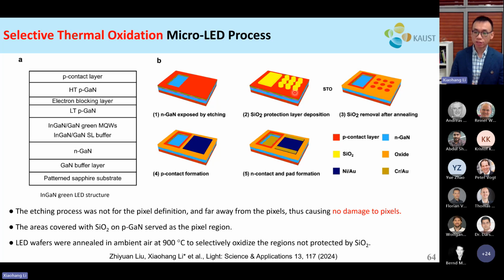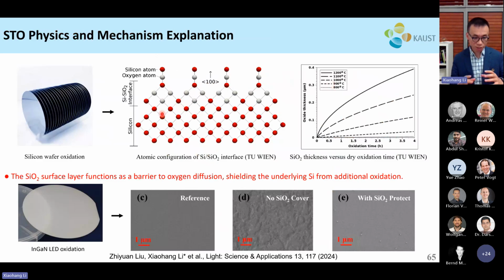And then after the oxidation, we remove the silicon oxide. So basically, the area below the silicon oxide is mostly not impacted. It still maintains the P-GaN PIN structure. But the area that is outside the silicon oxide protection layer will get oxidized by about a few hundred nanometers below the surface. Okay, so we utilize silicon oxide because silicon oxide is a very effective barrier to oxygen diffusion, right? So this has been used in the silicon industry as well.